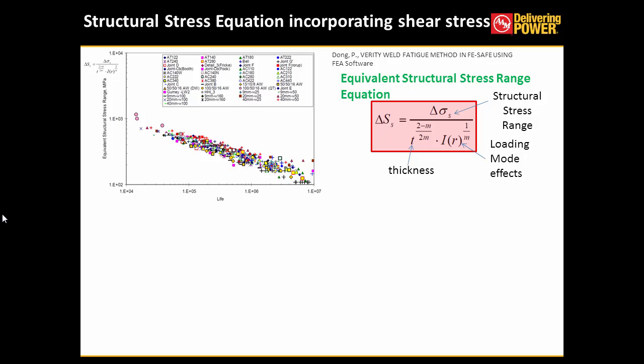So Battelle did thousands of tests, and most of the cases were related to mode 1 failure, for which only one component was required. That was the normal structural stress component. And when they used the thickness and loading effects, they were able to reduce the scatter in the data significantly. This I-R function, or the load mode function, has a fracture mechanics background, which is generating a bending ratio, which is calculated from a two-stage crack model.